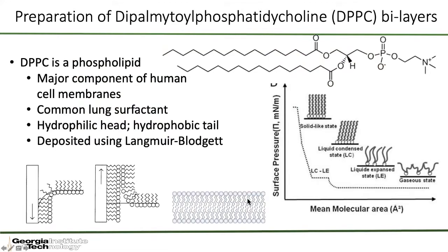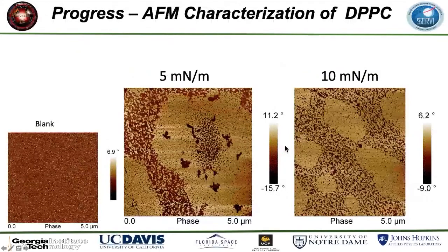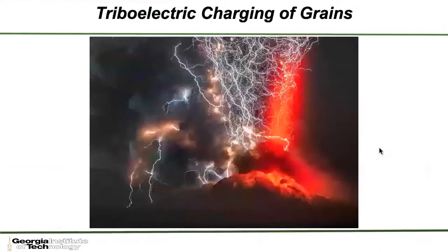Here's an image of some of those films that I took using atomic force microscopy. You can see the blank silicon film, pretty blasé, featureless. The deposited films have much larger islands, and you can see that we're getting quite a bit of DPPC deposition onto our samples. So then the next phase of this is to get these grains electrostatically charged.